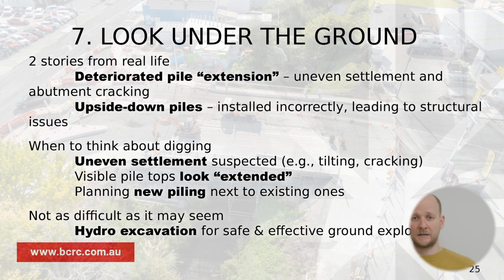The other story is about piles which were driven upside down. That might also happen. We were dealing with a bridge which was actually built in two stages. Stage 1 involved one lane, and it's a 3-span bridge as far as I remember. The other lane was built one year later. Because we were dealing with some corrosion issues in the tidal zone, we found that three piles on one of the piers of the second lane did look quite unusual. Once the contractor started breaking in, we quickly realized that there was no steel at all compared to the drawings available for this structure.